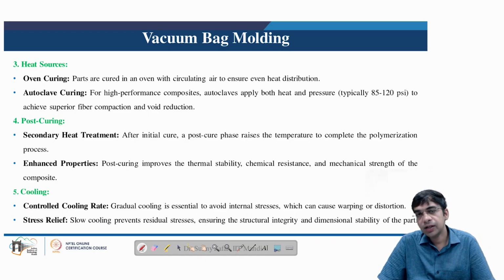Various heat sources can also be used with the vacuum bagging arrangement to accelerate the cross-linking. Oven curing is popular, where parts are cured in an oven with circulating air to ensure uniform distribution of heat. Or an autoclave may also be used for high performance composites, as autoclaves are able to apply heat and pressure of the order of 85 to 120 psi to achieve superior fiber compaction and void reduction. After curing, some secondary heat treatment may be carried out. This post curing phase raises the temperature to complete the polymerization process, which leads to enhanced properties. Post curing improves thermal stability, chemical resistance and mechanical strength of the composite.